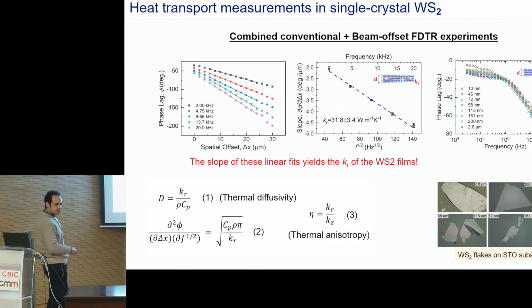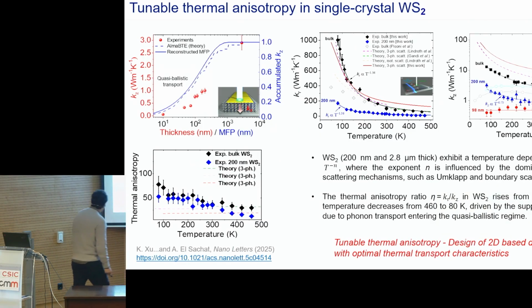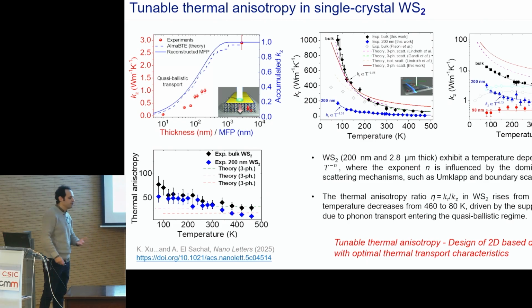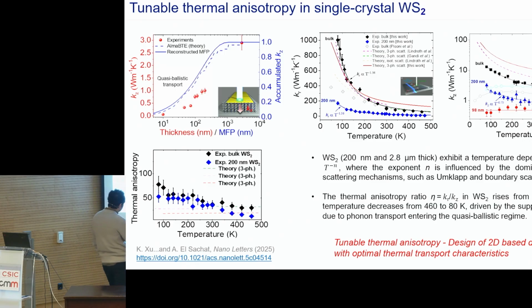So we did this for tungsten disulfide films, one of the first demonstrations, and we found a very strong dependence of the cross-plane thermal conductivity as a function of the thickness. We also calculated the accumulated thermal conductivity as a function of the mean free path. So actually this tells you which phonons propagate in our material. It tells you the percentage of phonons that contribute to the thermal conductivity with a certain mean free path. And in the other two graphs, you see the in-plane and the cross-plane thermal conductivity